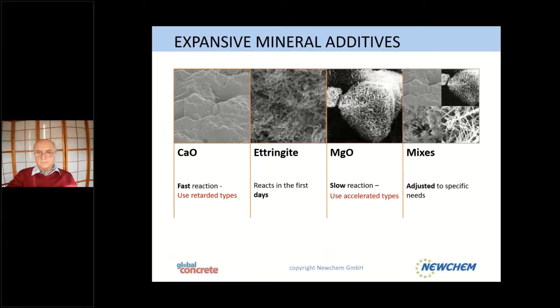Magnesium oxide, we started this about 3-4 years ago. This is normally a reaction which is very slow, and in the cement norm, magnesium is limited by 5% because it can give a late expansion after 10 or 20 years, cracking the concrete. So we looked into this problem. This is mostly because the magnesium which is in the cement is sintered, and therefore it will take a very long time to react. Either magnesium oxide or magnesium hydroxide are almost water insoluble.